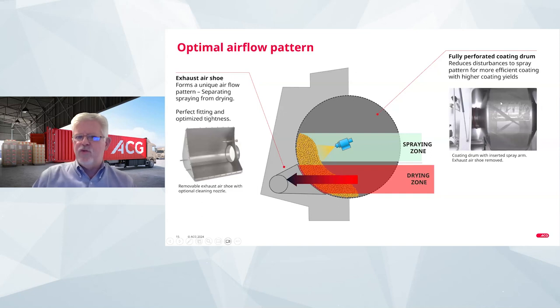One other aspect of the drum is providing a very large open surface area, yet still ensuring that you have mechanical integrity of the drum. Our systems utilize nearly 40% open area. And you can see in this photo to the right-hand side that you can actually see through the drum itself. You can see the baffles and the nozzles in this due to this large open area. This also helps ensure that we have a lot of control and flexibility over balancing our drying air in comparison to the amount of spray that we're adding and balancing the thermodynamics of the process.